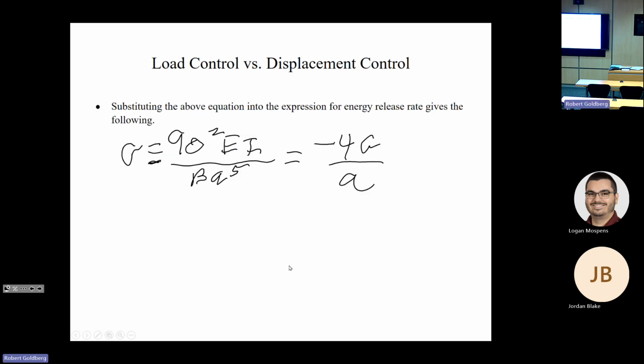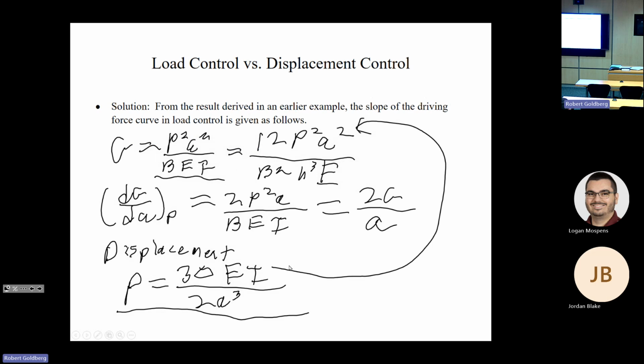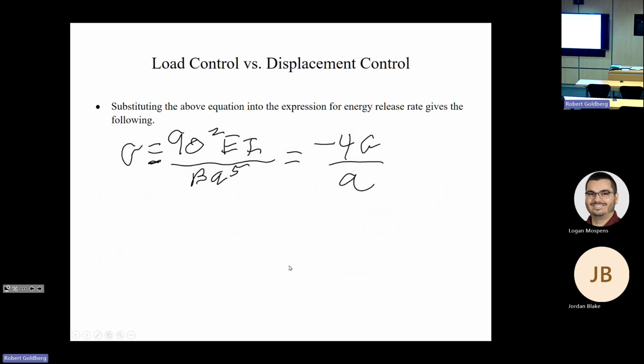So the point from this is that the driving force, the rate of change of the strain energy release rate with crack length, increases with load control because this is positive, and decreases with displacement control because this is negative. So for a flat R curve, like the example we talked about before, crack growth in load control is always unstable, while displacement control is always stable.